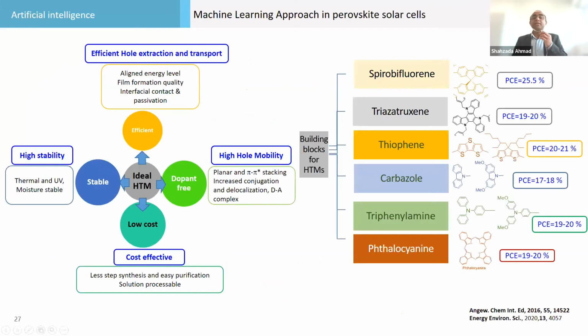If you look at the different families of hole transport materials, there is spiro-bifluorene, the commercial product, which is the most efficient and the workhorse, with 25% reported. Then we also found a new family, triazatruxene, with close to 20% reported. Then there are families well known for organic solar cells and semiconductors: carbazole, triphenylamine, phthalocyanine. These are the most reported families. HTMs from organic solar cells have been reported, and all of them are giving very good performance. But spiro-bifluorene, which is commercially spiro, is the most efficient one. But we have to develop new cost-effective materials, which can be made with simple synthetic steps, and they should have high hole mobility, stability, and efficient hole extraction.